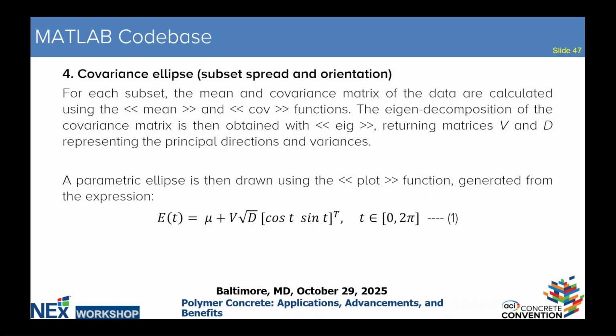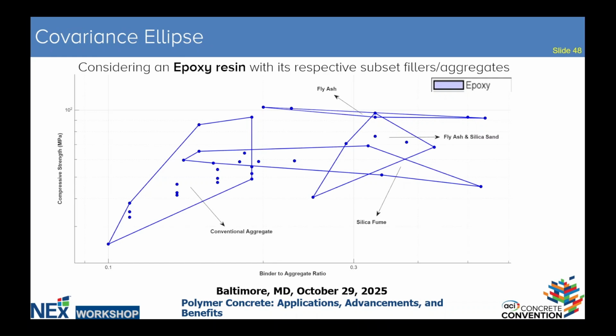So in the covariance ellipse, I had the data of each subset data, which I initially started with. I had the data plots being plotted here, so you can see, and I segregated them into each respective assignment. So we have the conventional aggregate, the silica fume, and the fly ash, silica sand, and fly ash. I use this one to elaborate for just epoxy resin for compressive strength data. The subset data for the epoxy resin was conventional aggregate, silica fume, and fly ash, and silica sand, and fly ash. We have all this data here, and we can't say that these are the real data of, let's say, conventional aggregates, or the real data of silica fume.